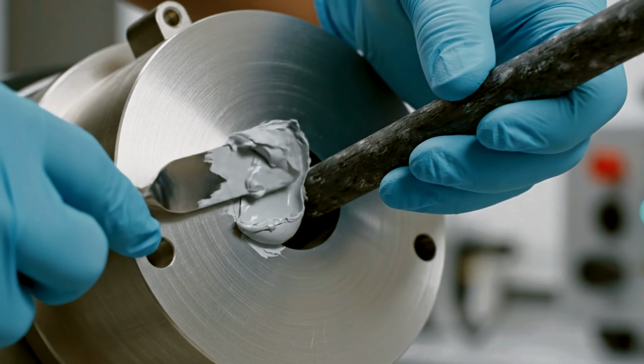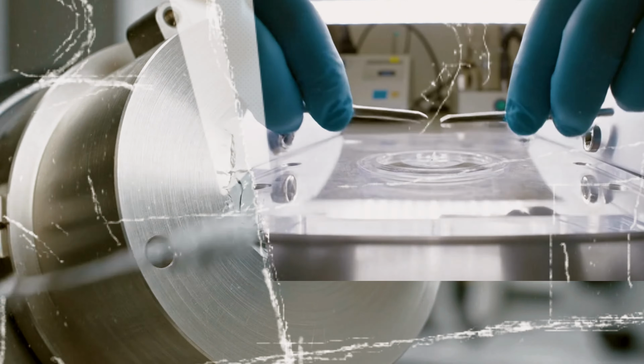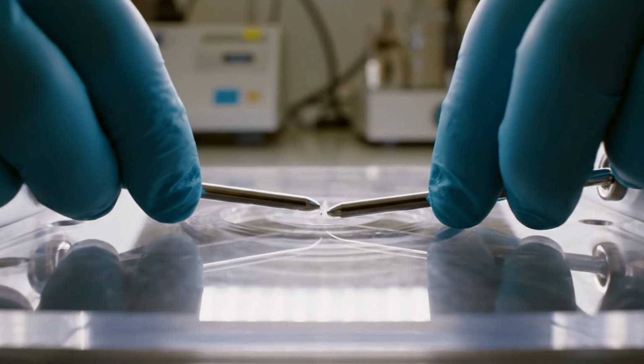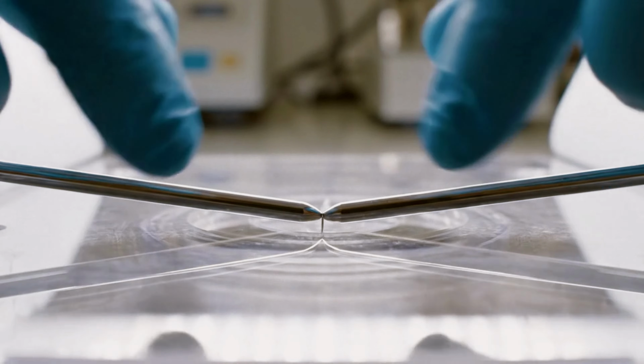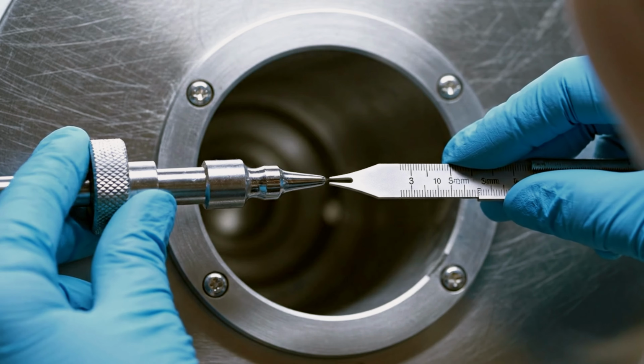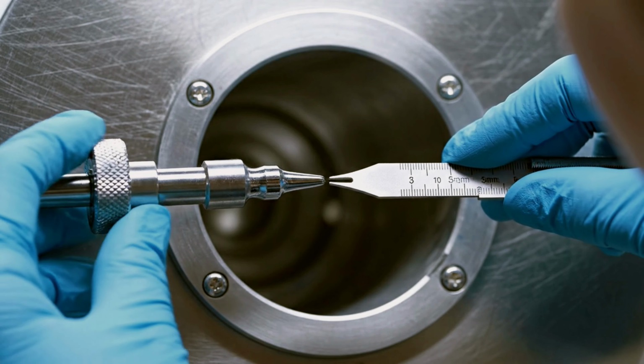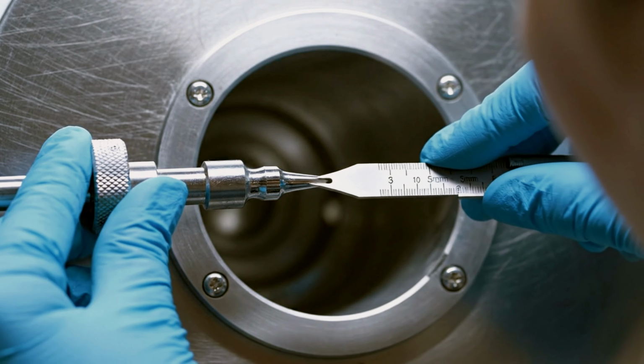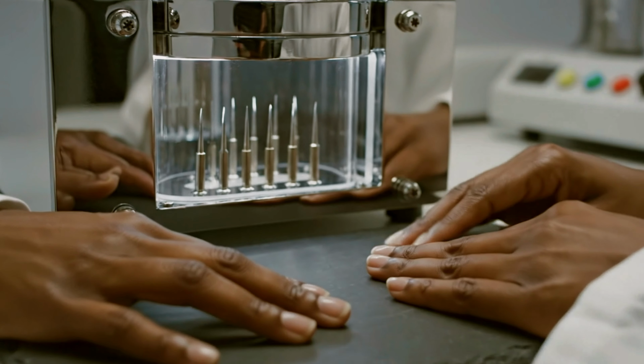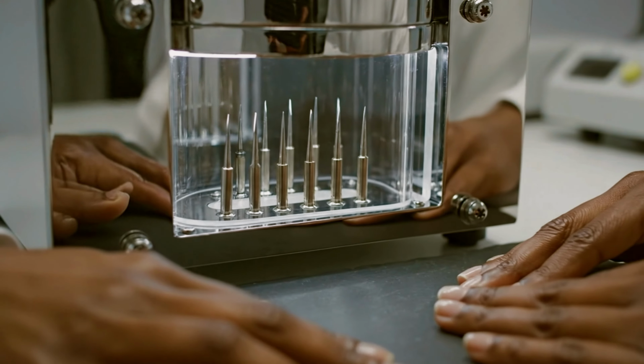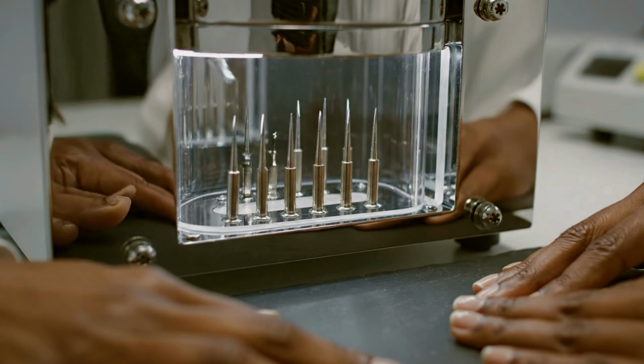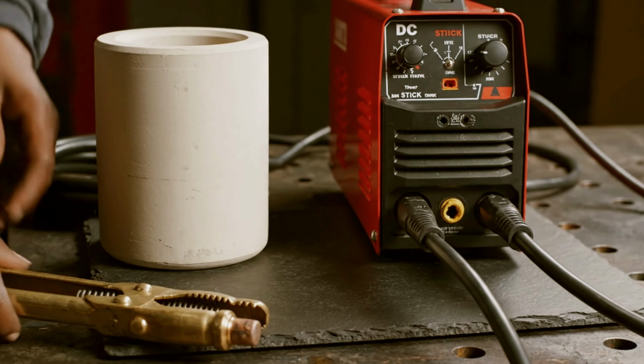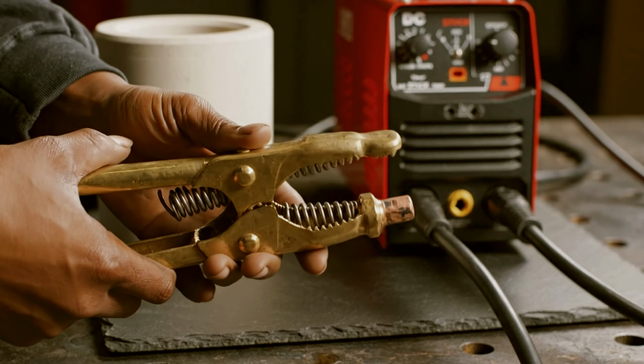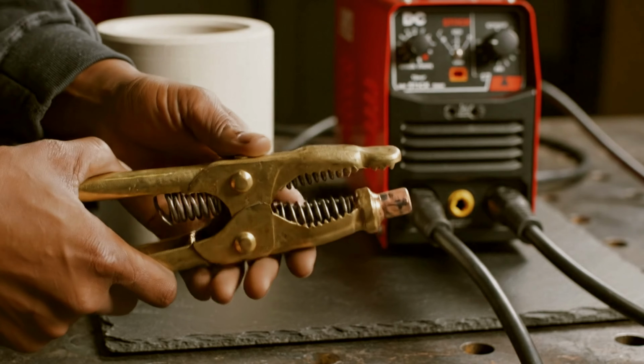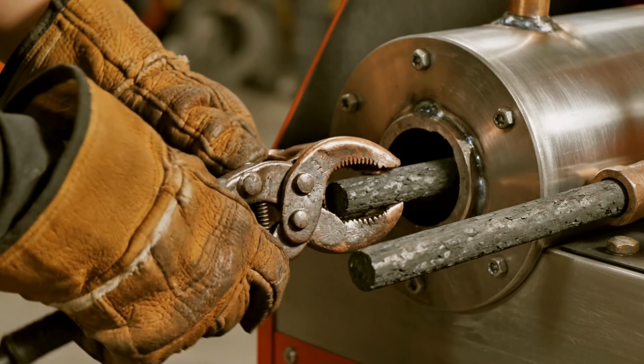The electrodes themselves are the heart of the whole system. Carbon arc gouging rods, the flat, copper-coated rods used in heavy metalwork, are ideal. They're made of compressed graphite. They conduct electricity exceptionally well, and they can handle the temperatures involved without degrading quickly. Each rod gets slid through one of the holes in the chamber wall and secured with a small amount of refractory cement around the entry point to seal the gap and hold the angle. The tips should sit about 3 to 5 millimeters apart at the center of the chamber floor. That gap is everything. Too wide and the arc won't establish cleanly. Too close and it won't have room to breathe.